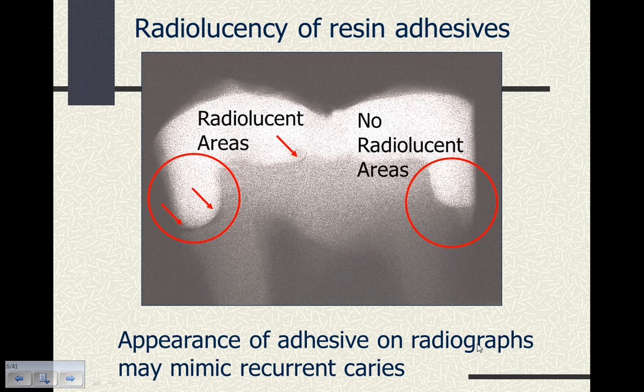Now, when we look at resin adhesive bonding agents with composites, here you're looking at a radiograph of a composite placed, an MOD, and what I'd like you to notice is that on the left-hand side, I see radiolucent areas. The arrows are pointing to these radiolucent areas. If I look on the right-hand side, the composite is well adapted to the cavosurface margin and the cavity preparation. There's been some concern recently that when placing a composite, especially a posterior composite, the adhesive would pool in the proximal box at the gingival margin, and that when we light cure it, we end up with a thickness of the adhesive. And in fact, the adhesive mimics recurrent caries. This is a very controversial area. In fact, many dentists, if they saw the image on the left-hand side, would be replacing that restoration.